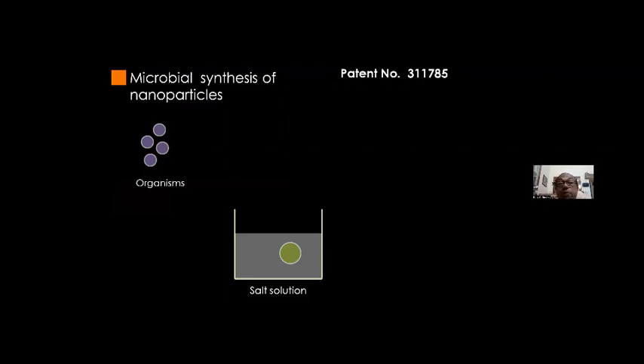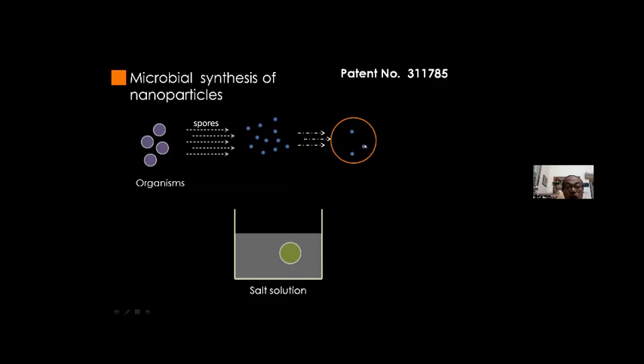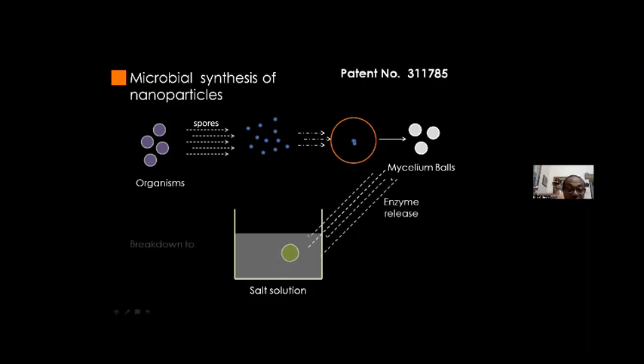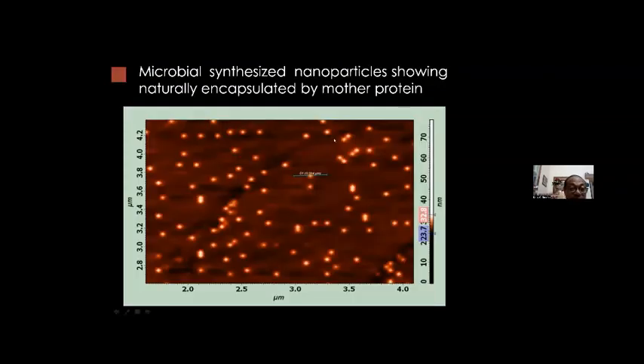Therefore, we have developed a microbial synthesized technique, or you can say biosynthesized technique, where we are isolating organisms from the native soil. This is our patent number. Then from their spores, we are making fungal balls. We make a microbial ball, and we allow that ball to release enzymes to break down our desired salts into nano. You can see it here, the enzyme releasing, and then the salt is broken down to nanoform. The beauty of this method is that, you can see it here, in the same image, each and every particle is naturally encapsulated by mother protein. So unless the protein layer breaks, they are stable. We found that easily under room temperature, the particles are stable for 1 year.